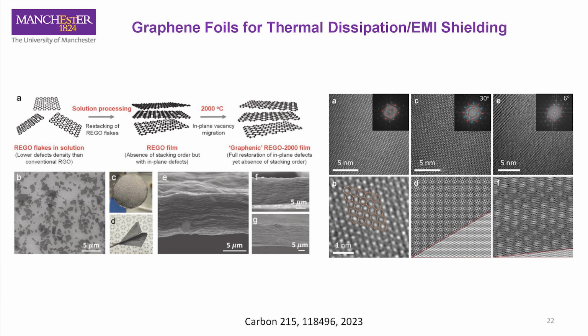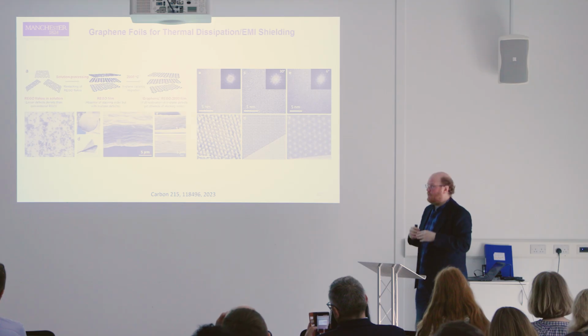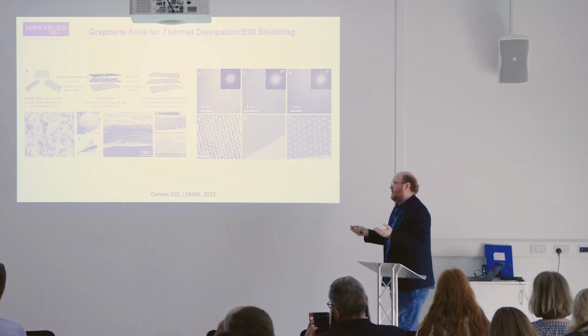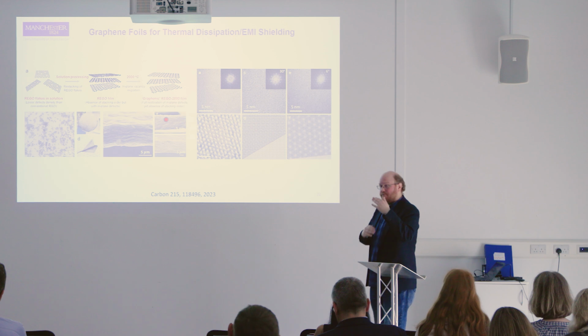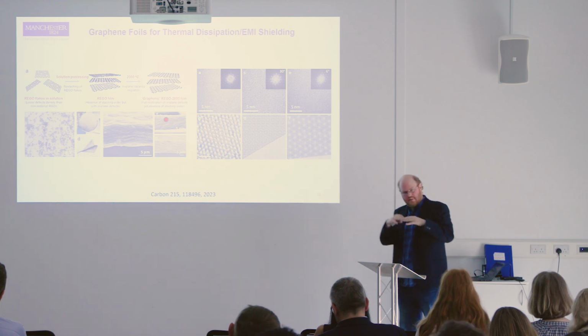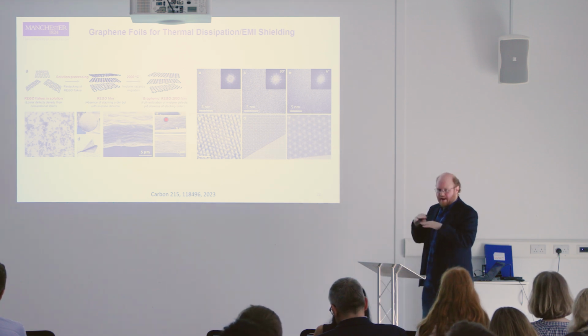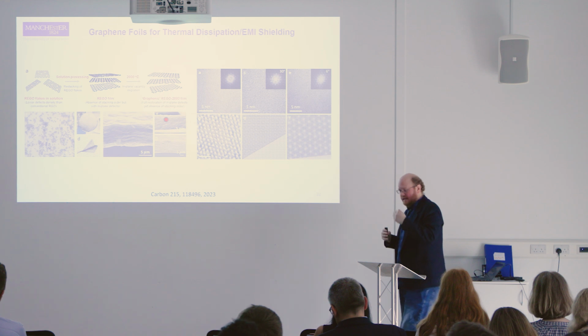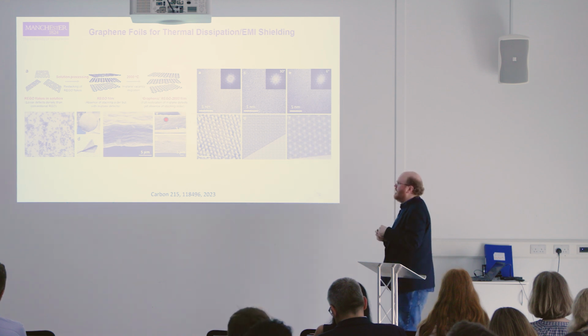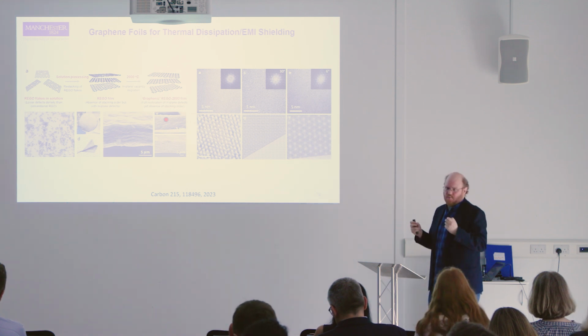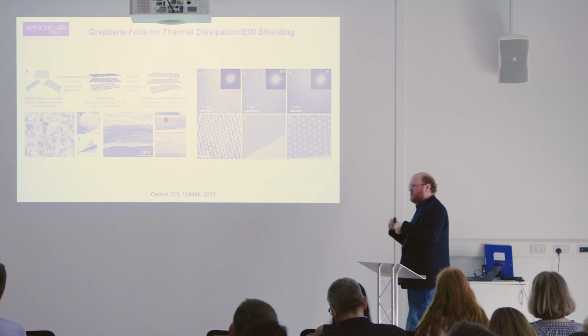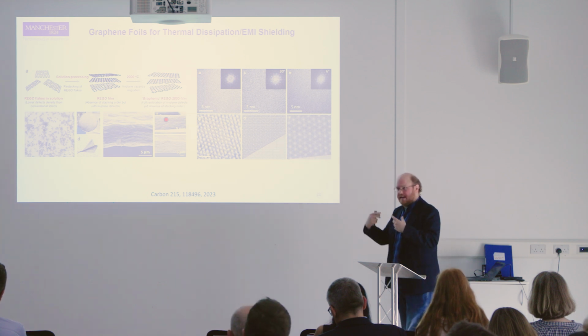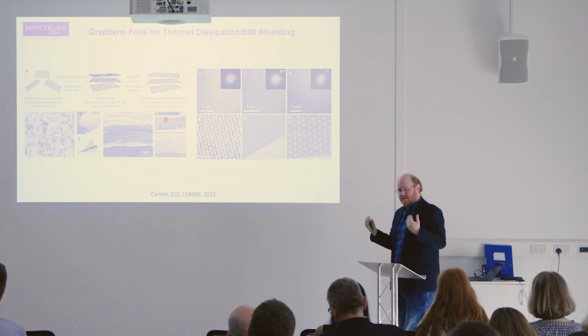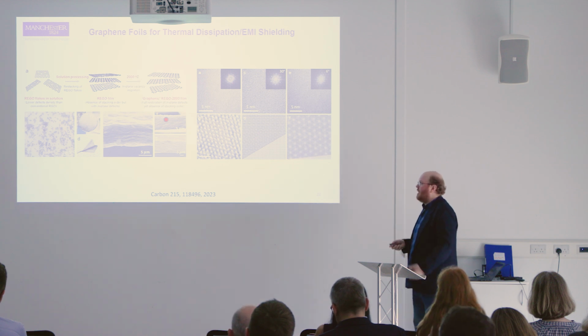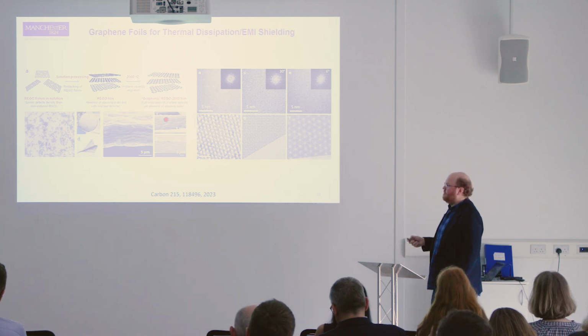In graphite, each of your carbon layers are very strongly interacting. They have this AB stacking, this Bernal stacking. If you take graphene, you disperse it and then restack it, you basically get a random orientation between it. And that random stacking basically gives you a very weak layer-to-layer interaction. And what that does is actually give you better thermal conductivity. So in graphite, you get thermal scattering, or the layers are kind of connected to each other. If the layers are independent of each other, the thermal conductivity is higher. And that's why these materials are of benefit.